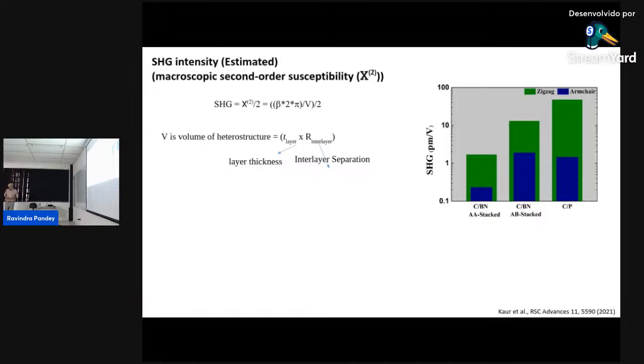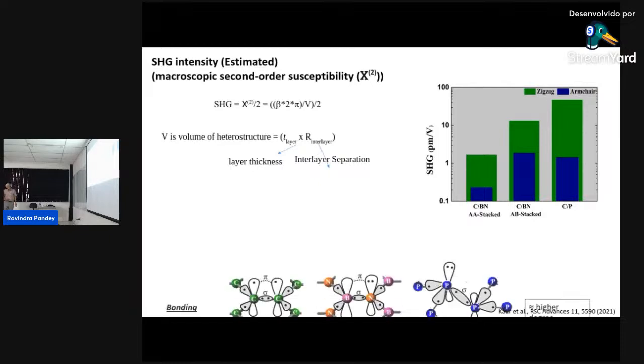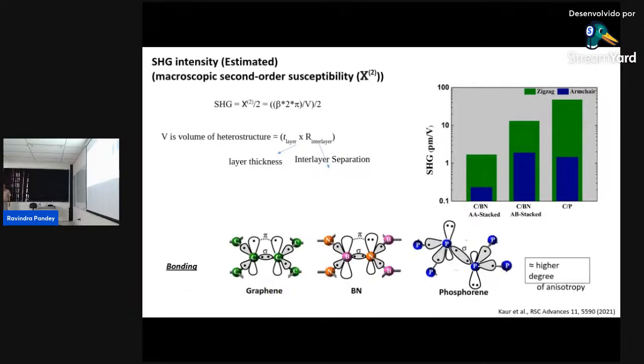You can see here this is the case with the phosphorene. This is the case with boron nitride. Because of this electron-rich phosphorus atom, it provides a larger perturbation in the graphene pi electron cloud, and that's why it gives a very, very high SHG value. And this again, like I said, is the graphene boron nitride, but this is the phosphorene. It provides a higher degree of anisotropy, which makes this heterostructure NLO.